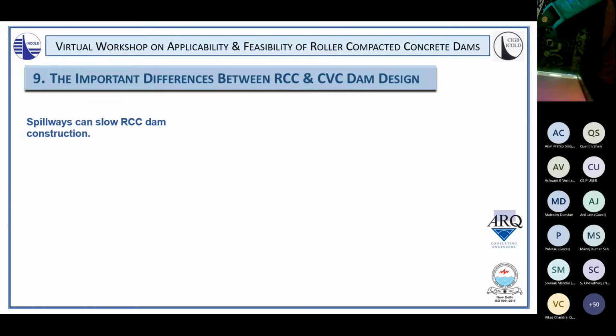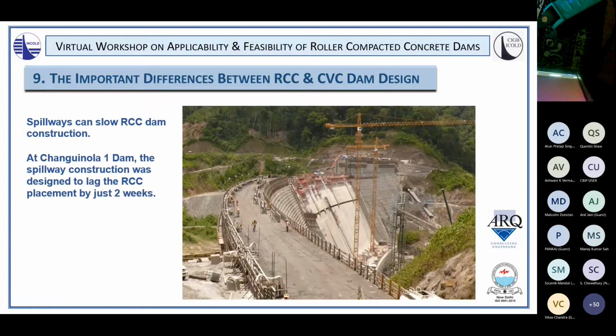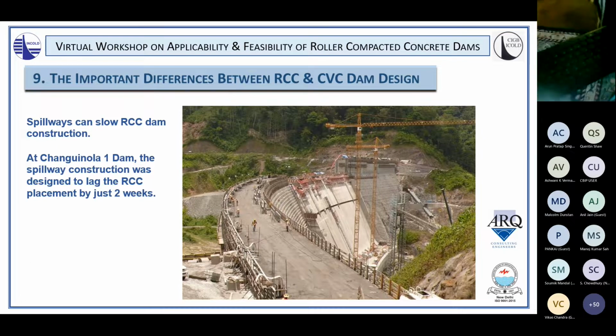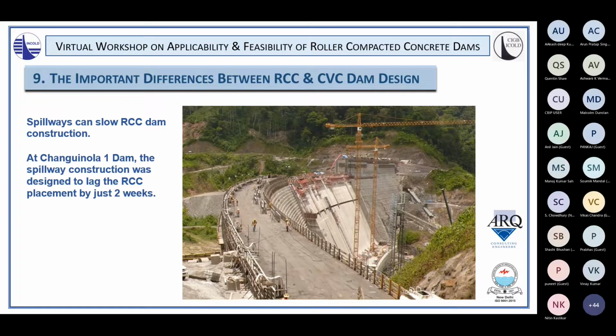So spillways can also slow RCC dam construction. And where you have a very simple traditional stepped spillway on an RCC dam with energy dissipation on the steps and in some sort of apron or other at the bottom, that has very little effect on the placement. But when you're looking at a system of higher capacity, where you can't dissipate over the steps, higher concentration of flow, or when you're dissipating energy at the crest, in these two cases, you can quite easily get into a situation where it significantly slows down the construction.